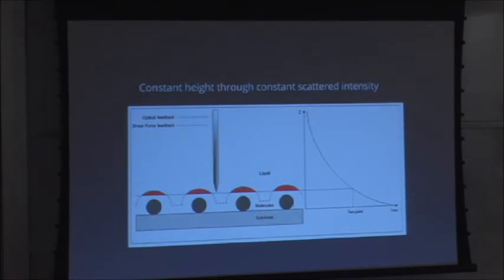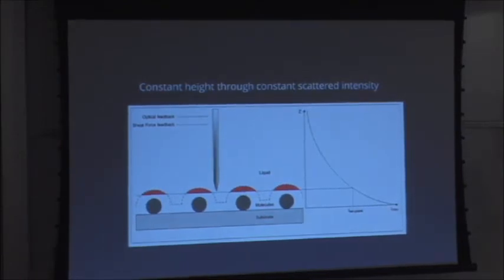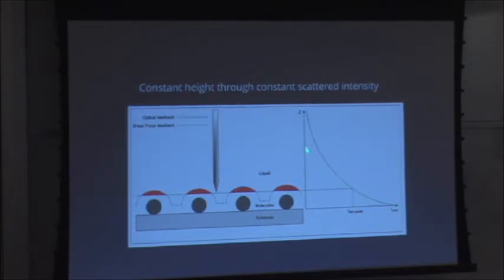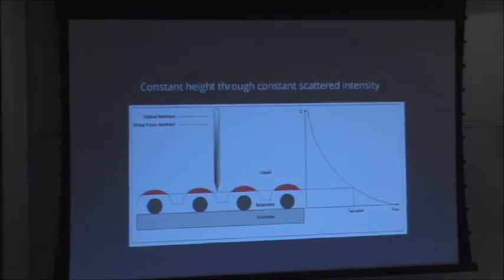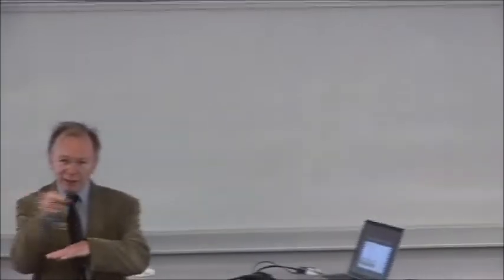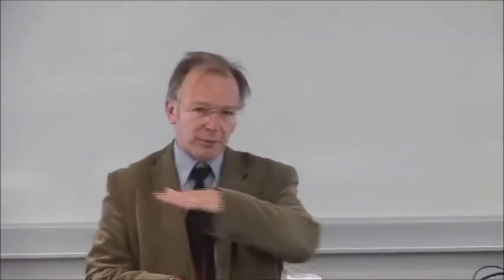There's another mode you can use it in. We've got that evanescent field, so we know when the probe dips into the field, it'll scatter, and the scattered intensity decays exponentially with distance, as is shown here. So as we move further away, the scattered light decreases. This is scattered intensity. So at a given level, we have a given intensity of light. That means we can fly across the surface at high speed without any feedback, except for the optical feedback. Just keep the intensity of light the same, so you're always scanning parallel to the plane.